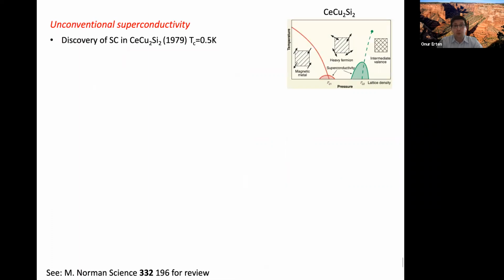The first unconventional superconductor discovered was cerium copper 2 silicon 2 in 1979. In this case, the TC is not really that high. So you might ask, how do you know that this is an unconventional superconductor? Why is this not a BCS superconductor? Actually, people knew very soon after the discovery of superconductivity in cerium copper 2 silicon 2 that it's not a BCS superconductor, because the Debye frequency exceeds the Fermi energy.